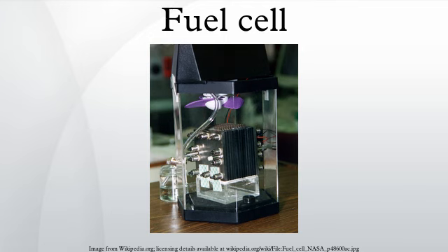According to their website, Ceres Power, a UK SOFC fuel cell manufacturer, has developed a method of reducing the operating temperature of their SOFC system to 500 to 600 degrees Celsius. They replace the commonly used YSZ electrolyte with a CGO electrolyte. The lower operating temperature allows them to use stainless steel instead of ceramic as the cell substrate, which reduces cost and startup time of the system.